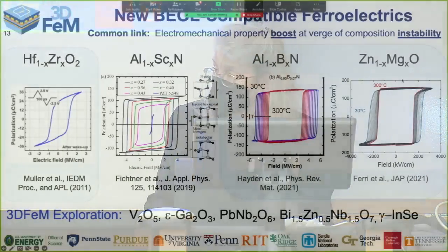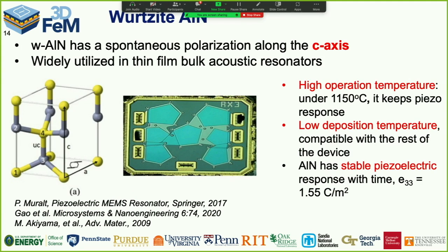It's hard. And so we've developed two analogs, aluminum boron nitride and zinc magnesium oxide, which undergo the same mechanism. We poise the material on the brink of a structural instability between the Wurtzite structure and the rock salt structure. And when we do that, these materials become honest-to-goodness card-carrying ferroelectrics. So very cool. We've also demonstrated that there's a bunch of materials that might have been ferroelectric that aren't, at least as far as we can tell. And that also turns out to be useful just to say, don't go here.